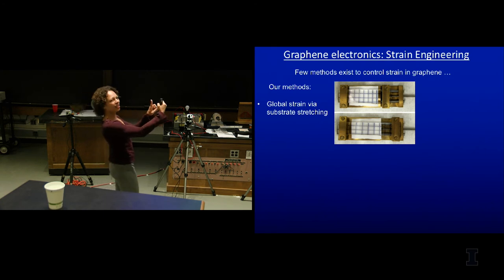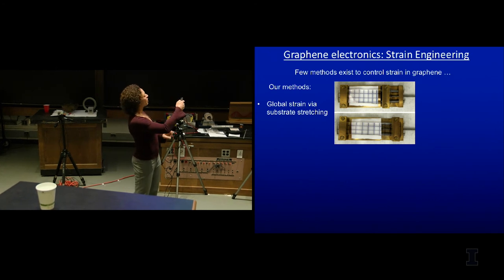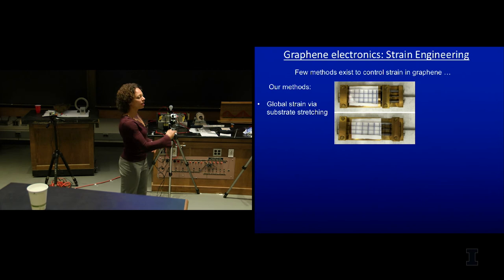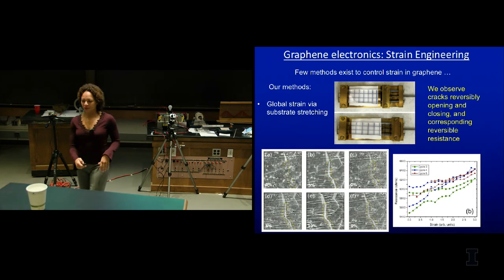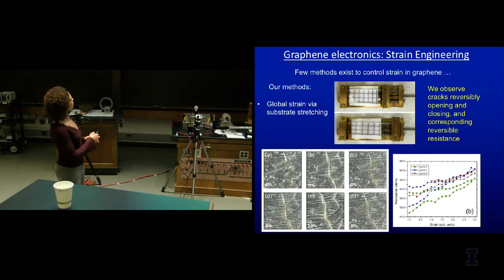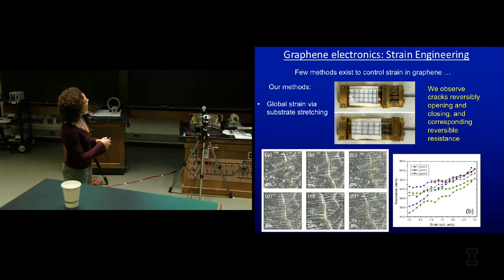That thing's about 2 inches long. And one of my undergraduates built this and then put graphene on it, stretched it, and measured its resistance. And actually what happened is we just created cracks in the graphene. And this is maybe a micrometer across here. But you can see as we stretched it, we got a crack. And we closed it, and the crack closed. And we stretched it more, we got more cracks. And you can see the resistance increasing and decreasing as you open and close the cracks.